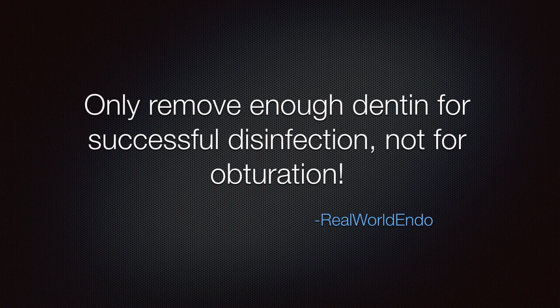And this is the idea of minimally invasive preparation, where now we are bound by the rule that we only remove enough dentin to disinfect the tooth and remove all the bacteria from the tooth, and no longer remove additional dentin just for the sake of obturation, which has been really the problem in the past with thermoplastic condensation techniques, which had required that we actually widen the tooth up way too much coronally only to accommodate our obturation technique, which was really unnecessary removal of dentin. If we could change our obturation technique with a bonded type of preparation, then we get away from that unnecessary removal of dentin.